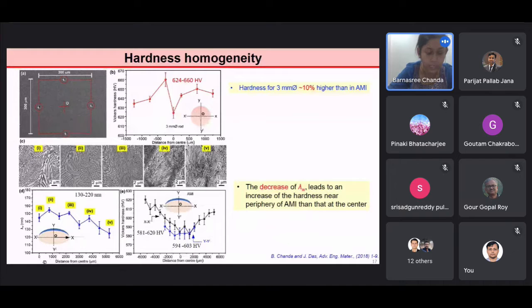We get a profile where, as we move from the center to the periphery, the average eutectic lamellae thickness decreases. Also, we further measured the Vickers hardness across the x direction and y direction, where at the center we get the lowest hardness, and as the average eutectic lamellae thickness decreases, there is an increase in the hardness. And when we compare the suction casted rod and arc melted ingot, the hardness for the 3 mm dia rod is 10% higher than the arc melted ingot.